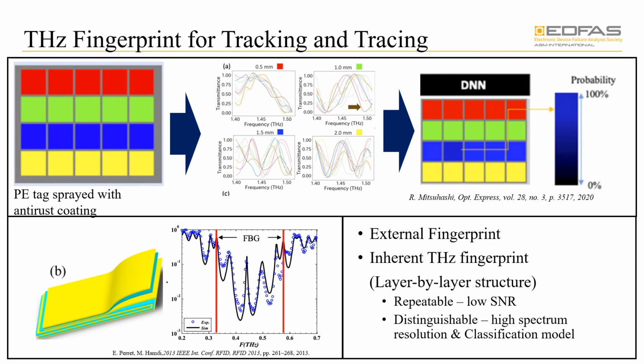As we hinted throughout the slides, some of the characterization information collected by terahertz systems can help us create a unique fingerprint. These fingerprints can be used for tracking and tracing of samples throughout the supply chain. In fact, we had in mind two different types of examples. We have the external fingerprint and then the inherent terahertz fingerprint. The external one would consist of a PE tag, which is sprayed by anti-rust coating, and this anti-rust coating will have different thicknesses and variances that are around 1 millimeter.